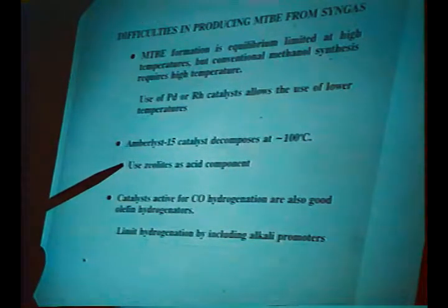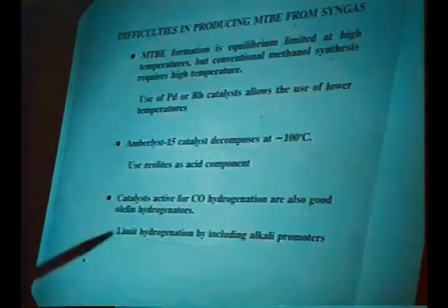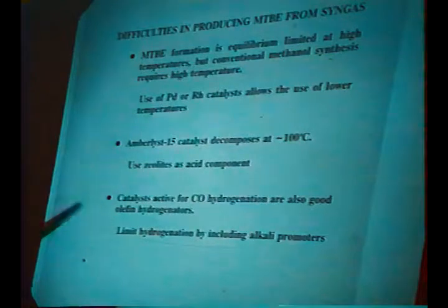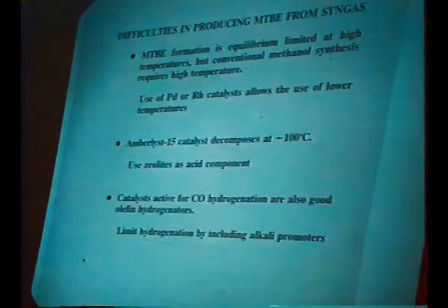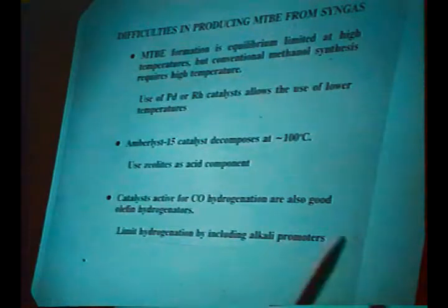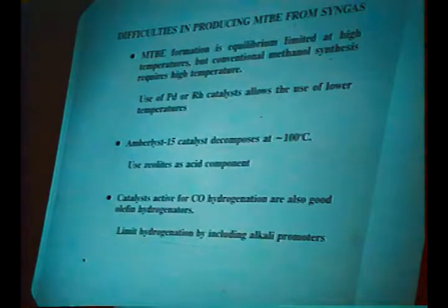The third problem is that we have a CO hydrogenation scheme going on, and we're trying to add an olefin to it. Any catalyst that is capable of hydrogenating carbon monoxide is also a good olefin hydrogenator. So you have competing reactions of trying to react isobutylene with methanol, while at the same time the catalyst is trying to hydrogenate your olefin. We dealt with that by including alkaline promoters in our metal catalyst to try to reduce its hydrogenation ability.